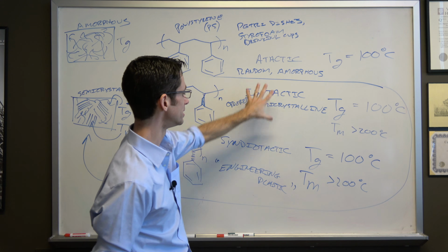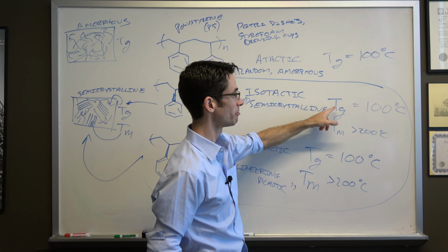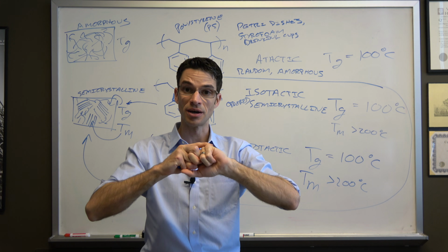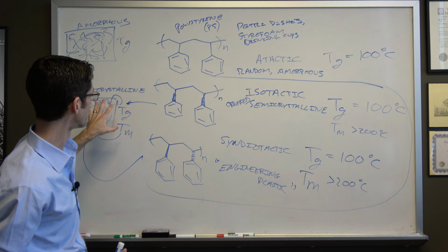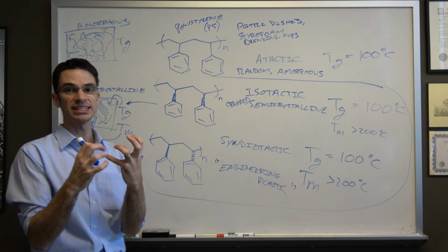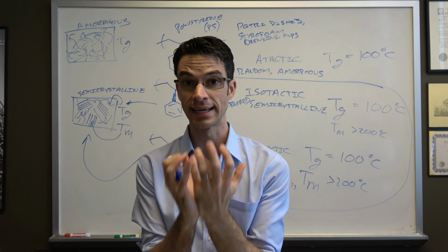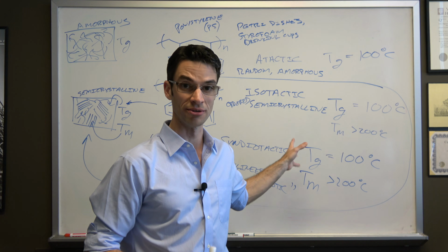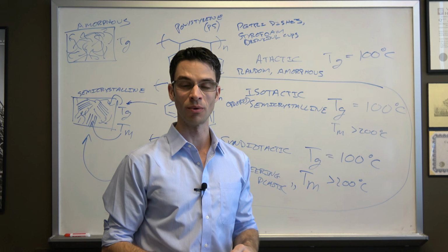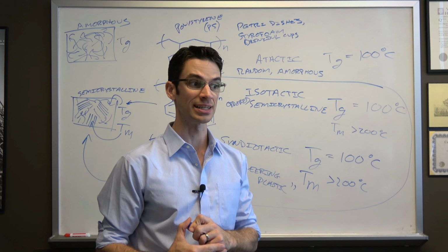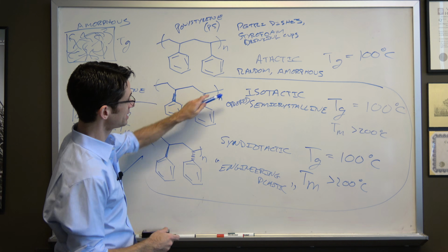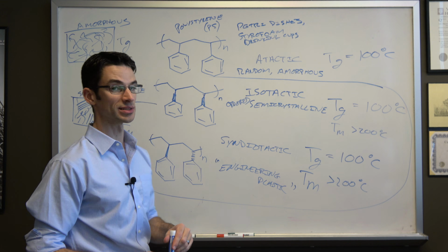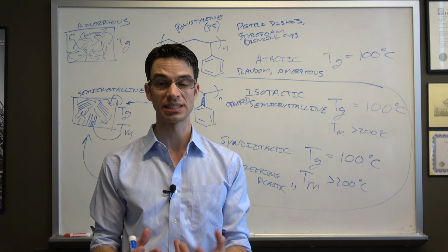Whereas if you have one of these two materials and you increase the temperature past the glass transition temperature, you're still below the melting temperature of these crystallites, and the crystallites serve to hold the material together. So that's very useful. This isn't the only engineering plastic, it's one of thousands, but it's one of the ones that's particularly famous. So of these two, it turns out that syndiotactic polystyrene is more useful because it has faster crystallization kinetics.